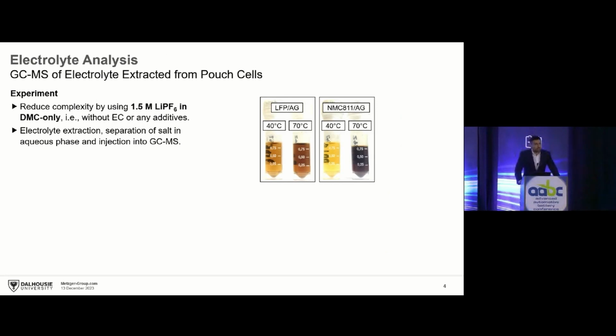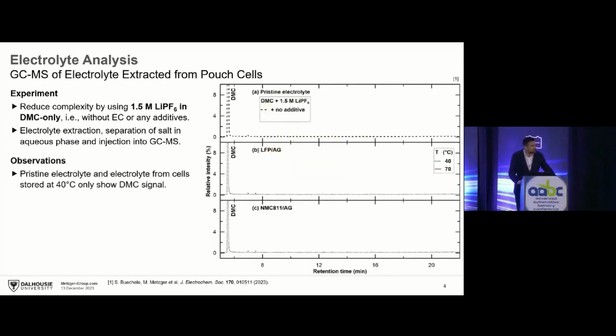So we did a chemical analysis by gas chromatography on these electrolytes. Basically, this is a nice technique that allows you to identify the molecules that are created in the battery cell. So in order to make our life a little easier here, we just use a simple electrolyte formulation that only has DMC, dimethyl carbonate, as the solvent. We have no ethylene carbonate here. That sort of simplifies the gas chromatography analysis, but you see the color change is very similar for this electrolyte. And now we can basically take these exact electrolytes that you have seen in the picture and we put them in the gas chromatography machine.